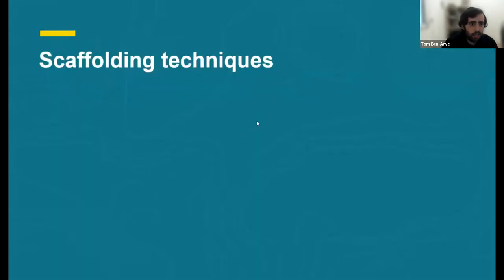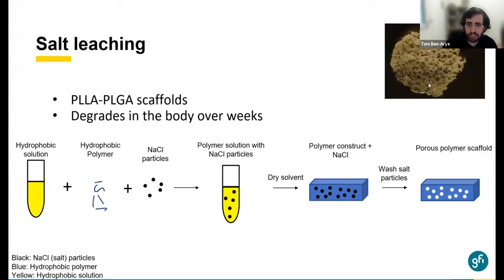Let's discuss a little bit the scaffolding techniques. The PLLA-PLGA scaffolds that we saw before are generated using salt leaching. This is an example of a scaffold made like this. This is a technique used in order to generate hydrophobic, porous scaffolds. Basically, you take a hydrophobic solvent and a hydrophobic polymer that will generate your final sample, and you mix them together with salt particles. The salt particles will generate the pores that you will have at the end. So when you combine the three of them, you generate a polymer solution with the salt particles. And if you now dry the solvent, what you will be left with is the salt particles inside of a polymer construct. And if you wash this with water, basically you will get a scaffold like this, where each thing that you see here is where a salt particle was.